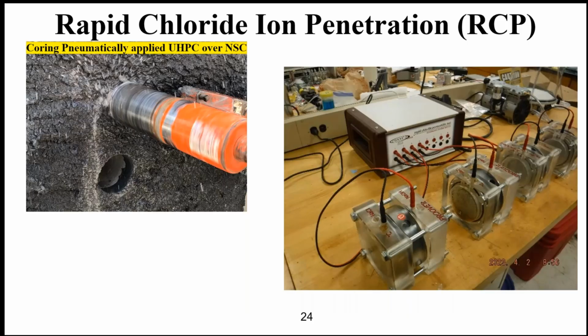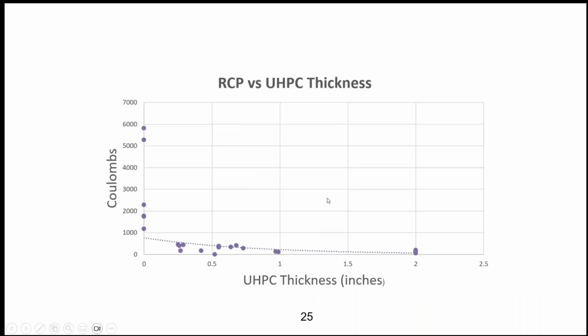We have taken cores out of concrete that has been sprayed, and then we have done the rapid chloride permeability test on these. This slide shows you the data. For example, if I don't have anything, just plain reinforced concrete, the number varies depending on the concrete. I mean 2,000 to 3,000, even some very large numbers. But if you apply just 0.5 inch of sprayed UHPC, you can see that it's going down. When you get to one inch sprayable or 0.75 inch, you are looking at 200 to 300 coulombs for the RCP numbers.